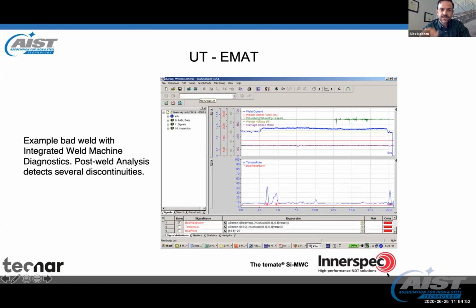And here's a case of what we could consider a bad weld. Again, there were some changes in the welding current here, as we can see in the upper chart. And in the bottom chart, we got at least 3 spots of backscattered sound, enough for the operator to say this needs to be re-welded. It all depends on the threshold, on the recipes of the clients. From then on, it could be an automated decision or it can be a human decision, but at least it's a relatively reliable inspection of the volume.